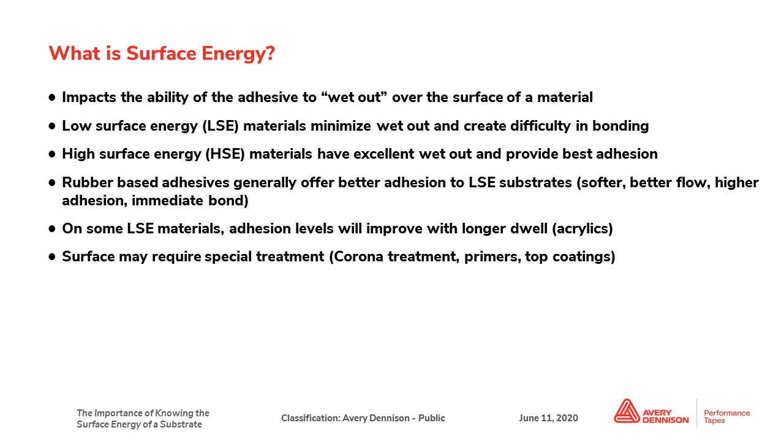Low surface energies minimize that wet out, and they're more difficult to bond to, as you've been seeing. And high surface energies are the opposite. They have excellent wet out properties and provide the best adhesion. So as you've seen in the charts too, rubber adhesives generally offer better adhesion to low surface energy substrates because they're softer and they flow more. But when it comes to acrylics, which are generally firmer adhesives, they don't flow as much, meaning they need more time to dwell and flow out over the substrate. And sometimes they're just too firm to bond to different types of low surface energy materials, and you won't get a good bond, as I'll show you some examples of that soon.